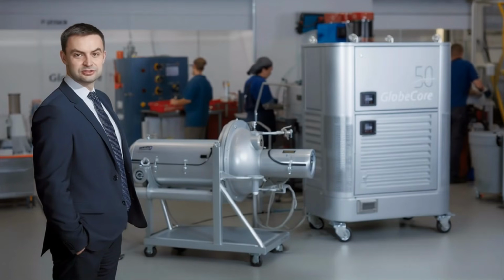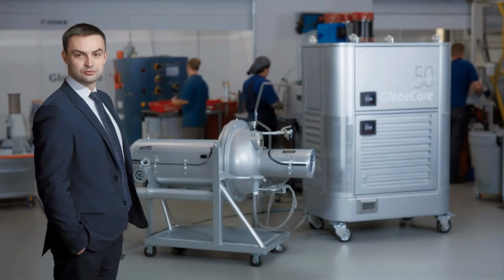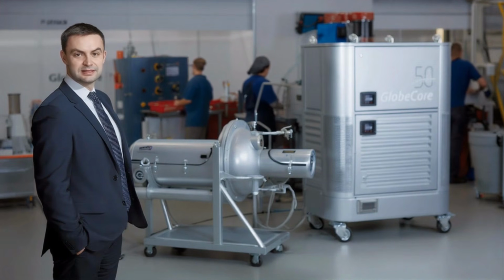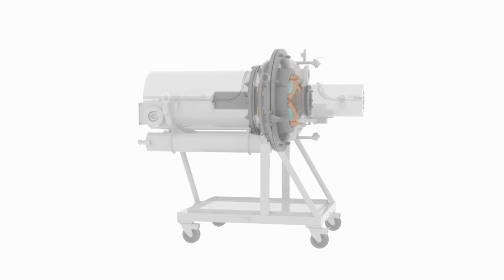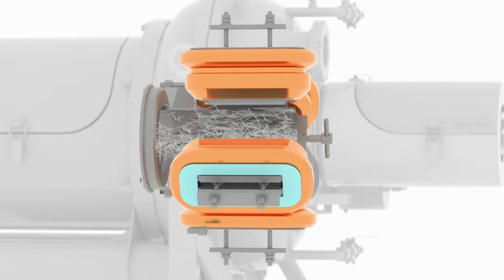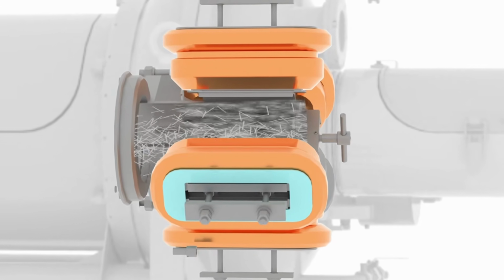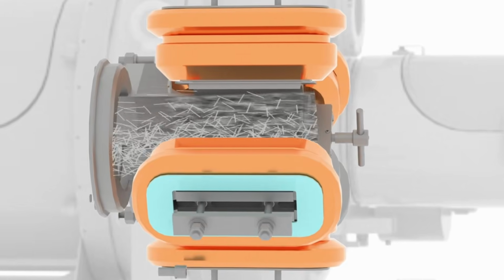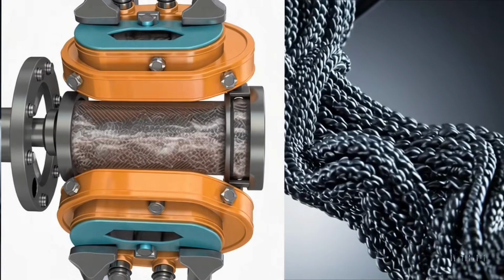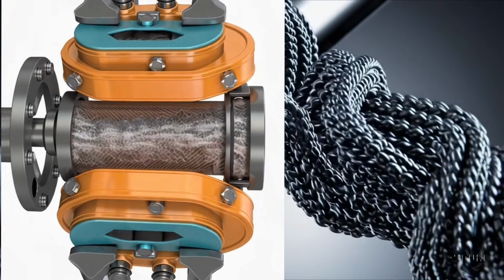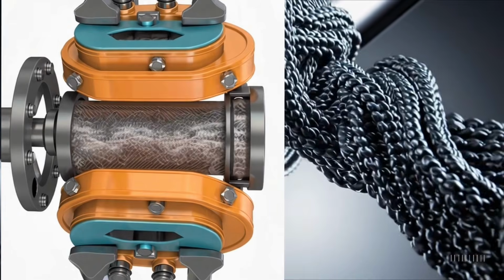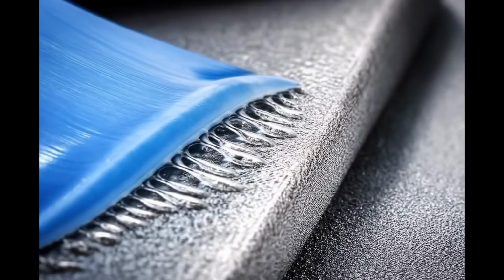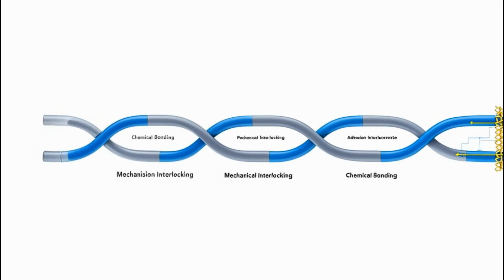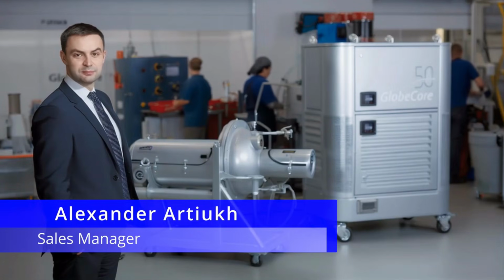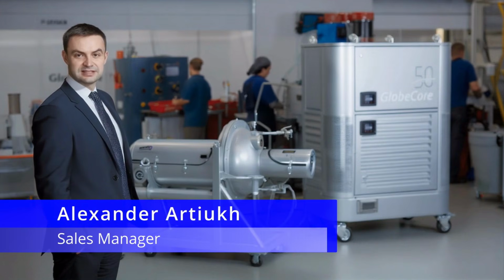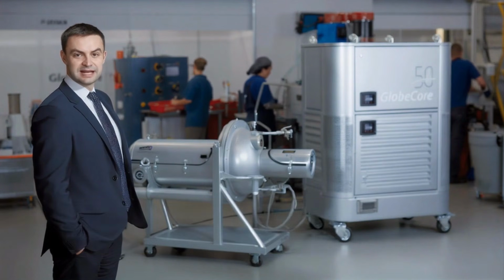The key to the efficiency of AVSp is the action of the vortex layer in an alternating electromagnetic field. In the reaction chamber, ferromagnetic elements move chaotically at high speeds, creating intense local impacts, shearing, and micro-deformations. As a result, not only dispersion occurs but also activation of the particle surfaces. This increases adhesion between the polymer and the metal and ensures stable fixation of the filler.